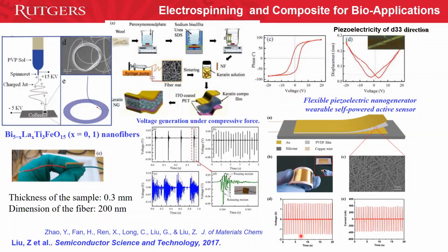Electrospinning is making a lot of noise. Electrospinning is not new. We worked on electrospinning of bismuth ferrite nanofiber, and Ruth Rivera is in the Martin Marietta now. And so by simply putting your solution, whatever nanoparticle solution in the particular polymer here, and by applying electric field, you are simply creating nanofiber here.